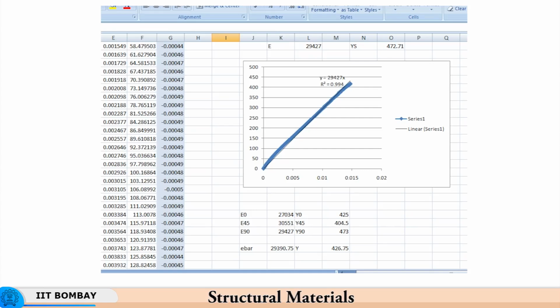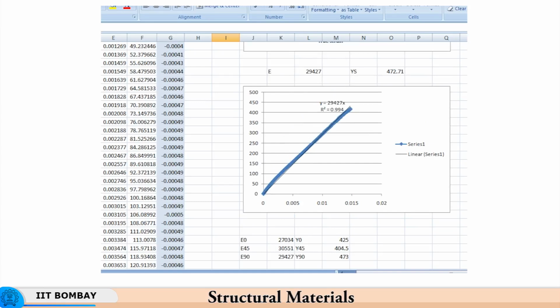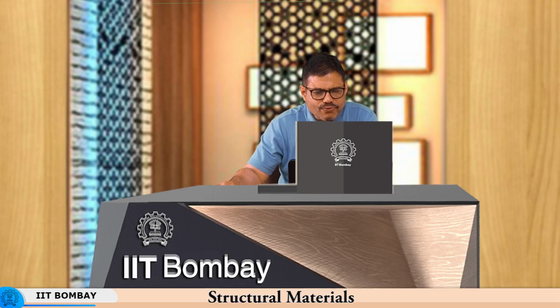You will see that the Young's moduli differ in different directions with respect to rolling. So, if you have the rolling direction, transverse direction and the direction of 45 degrees, the yield strength changes, and the Young's modulus also changes. So, the properties of the material differ between the rolling direction, transverse direction and the direction of 45 degrees. This shows that there is a directional dependence of the Young's modulus and the yield strength as well, and you therefore calculate the average value. Now, this Young's modulus has not been calculated using an extensometer. This is 29427 MPa as the Young's modulus. You can get accurate values once the measurements of the elastic strains are made using an extensometer.